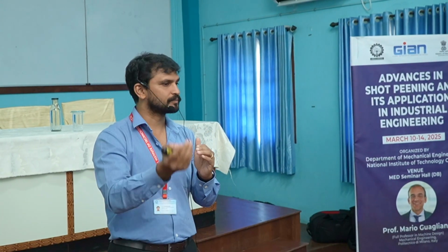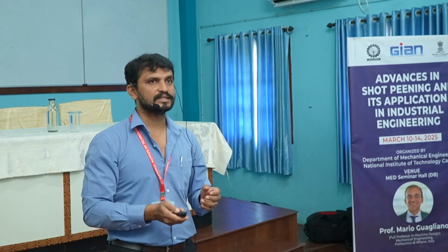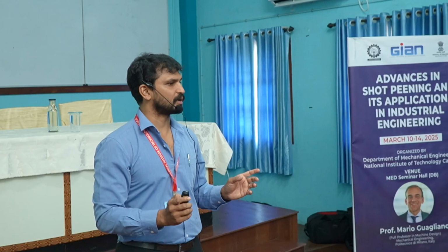Then powder feeder temperature and temperature uniformity, all these things are very important. These are some of the process parameters. Here you can see again the schematic representations of these things. So here you can see that the distance between the two tracks is called the hatch distance, and the scan velocity means at what velocity this laser beam is moving. Then the layer thickness is the distance between the two subsequent layers, the height of one layer. This will be exactly the same as in the pre-processing stage. How did you slice it? That will be matching with this.